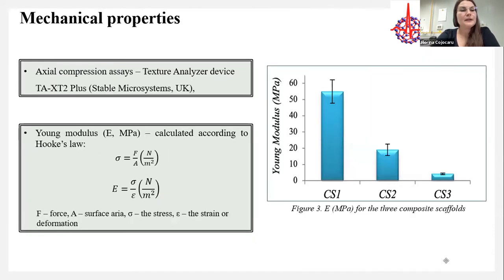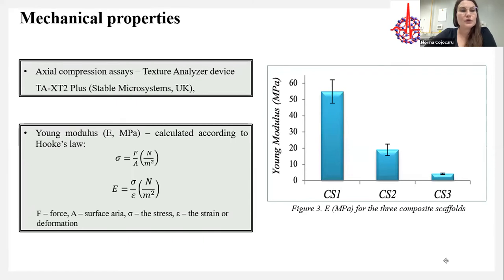The mechanical properties were studied by compression assays with a texture analyzer device, and we calculated the Young's modulus according to Hooke's law. As can be seen in Figure 3, the values obtained for our scaffolds fall within the range of values of natural trabecular bone.